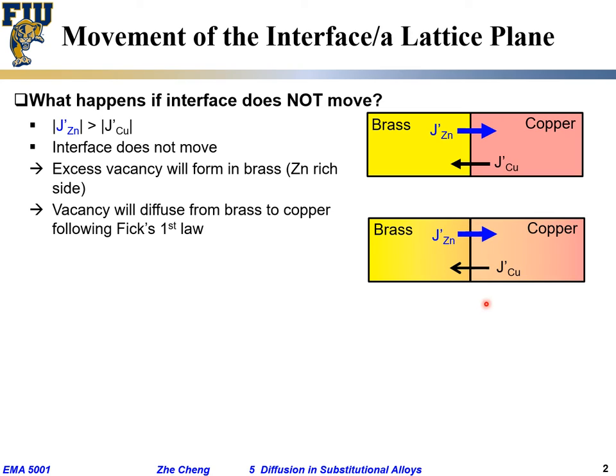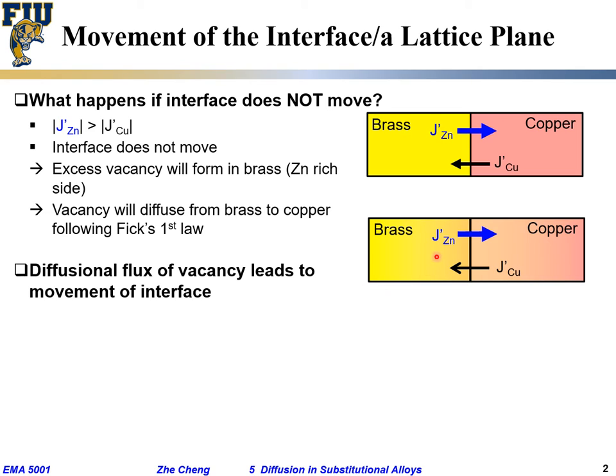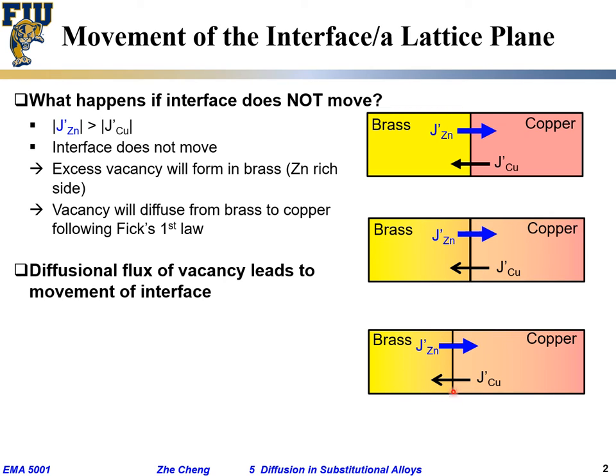Make sense? If this interface doesn't move, I'm going to leave a lot of vacancy, but quickly that vacancy has to go somewhere else. Make sense? As a result, if the vacancy moves towards the right side, this would lead to the so-called motion of the interface. I have a lot of vacancy, the vacancy moves. This interface has to actually move towards the left. I'll put it another way. The copper goes, it leaves the vacancy. If this doesn't change, the vacancy moves, or the vacancy collapses, the interface is going to move back. Do you see the point? If the vacancy collapses, it's essentially that this interface has to move backward.